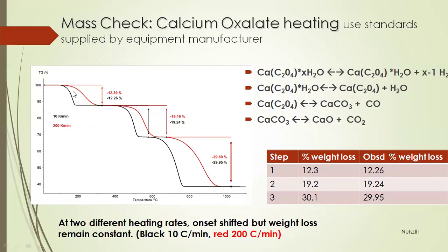Now you can see there are 2 curves I have shown purposely. One is black, one is red. The red is the curve of calcium oxalate heated at a rate of 200 degrees centigrade per minute. This is to show you that if you increase the heating rate of your sample, the total behavior of your TGA curve is going to change. Weight loss will remain the same: by heating the calcium oxalate at a higher rate, instead of 12.26, I got a weight loss of 12.39. And in percentage, it is 12.3 and 12.4%. But if you see the TGA curve nature, my onset of degradation and curve nature is totally changed.